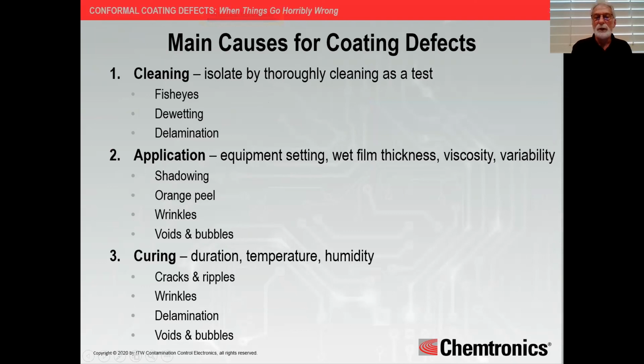Okay, here's a different take on that same chart that we had earlier. And now what we've done, we've kept the main three categories of generic causes here. But we have included these conditions that we've gone over, and we've categorized them according to a cleaning issue, an application issue, or a curing issue. Now, they're not mutually exclusive. If you can see, delamination can be caused by a cleaning problem. It can also be caused by a curing problem. That's why we put those little symbols up there. Sometimes there's one little symbol, sometimes there's multiple symbols. But hopefully, this has given you at least some areas to investigate so you can resolve that problem.